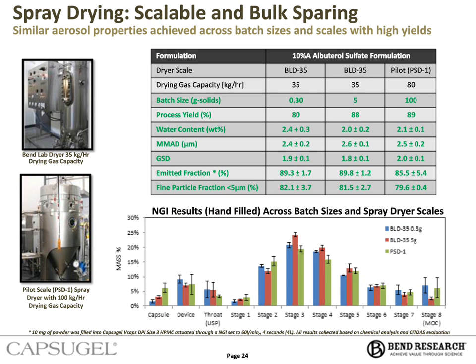So again, we see very similar aerosol performance in the table there, and then the actual deposition profile from the next generation impaction tests in the graph below. So again, across the different pans or stages of the NGI, we see a very similar deposition profile. And these results are with hand-filled capsules at 10 mg fill weights.